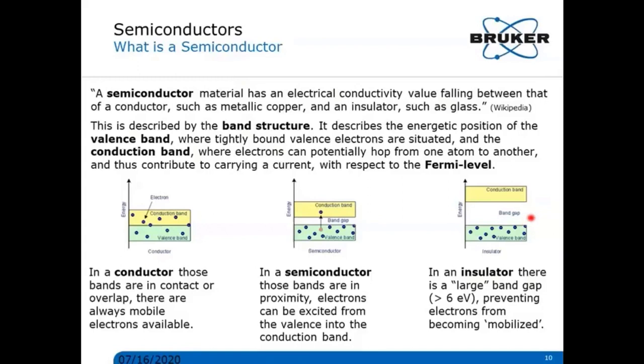an electron from the valence band into the conduction band, and this is basically insulating at normal conditions up to a certain breakthrough voltage or very extreme conditions. But in between, we find now the semiconductor, where those bands are still separated, but are close enough to each other so that with typical photon energies of visible light or with thermal excitation, we can generate now carriers that can carry a current, and as well we will generate holes in the valence band that can as well contribute to the current by basically respectively being filled from neighbors and thus moving in the opposite direction of the electrons